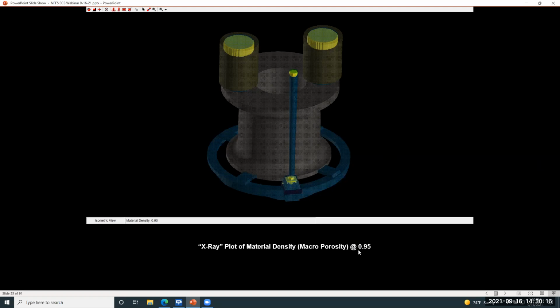Here we're plotting at 0.95, so it's a higher sensitivity. Anything is shown that has lost more than 5% of its nominal density. 0.99, this is 1%. We can see we're getting a little indication here at the gate connections. And then finally, at a value of 1, this is our highest level of sensitivity. In other words, any degree of loss of metal density will be indicated in the plot. So we can see that we have more indications in the sprue. We can see better the piping of the risers, but we can also see that the casting is completely clean.